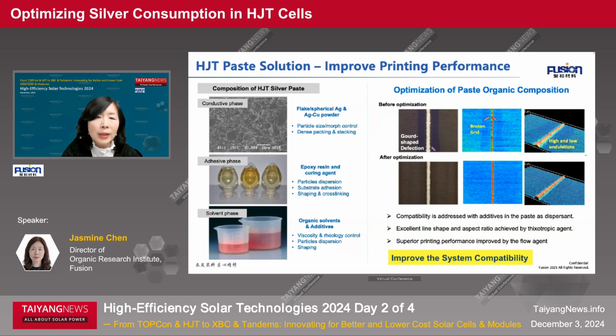For the composition of HJT silver paste, you can see three types of components in the formulation. One provides the conductive phase, which is always silver, the metal, silver or silver coated copper powder. The second one is a resin; we usually use epoxy resin. And the third one is the organic solvent and additives.